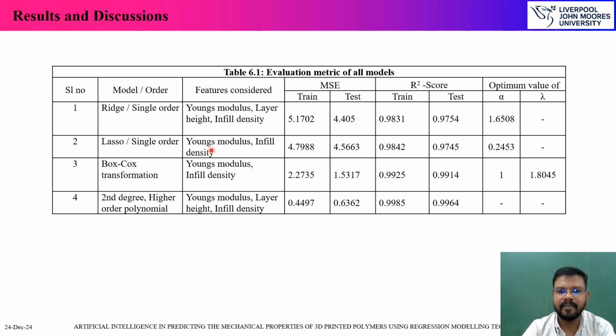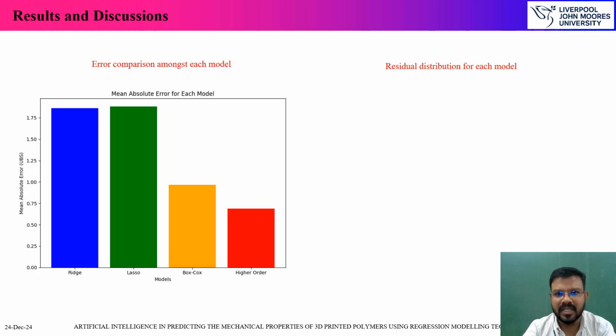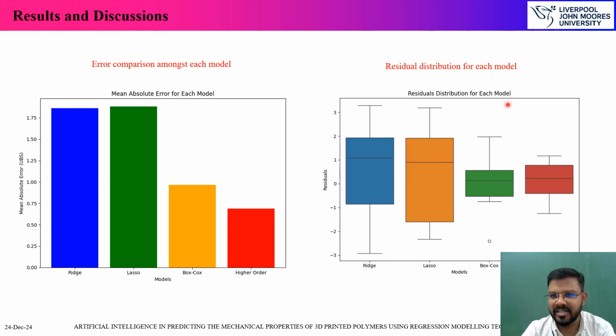Similarly for the lasso model. Now, as I told you, there was a drop in the mean square error value as and when we moved ahead in the ridge model, lasso, Box-Cox, and higher order polynomial equation. So this is where we get to see the higher order polynomial equation had a minimum mean absolute error value, followed with the residual distribution of each model, wherein this is a slight unbiased distribution what we see here.